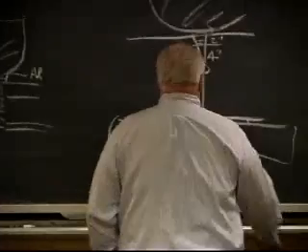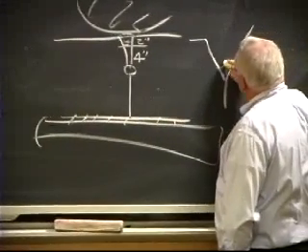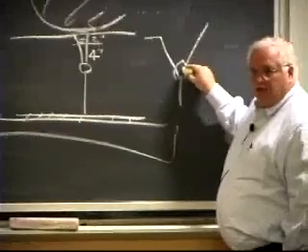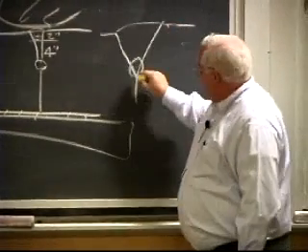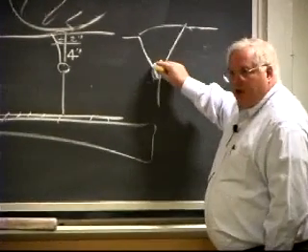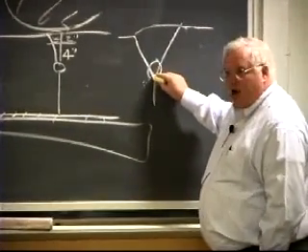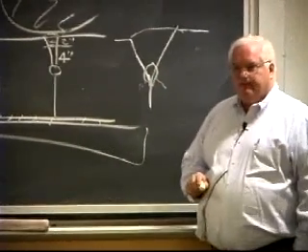Yeah, I got a question. I don't know much about materials, so tell me about when you drill that hole, what are you getting rid of? I'm getting rid of, well, at a root pass, when I'm doing an arc weld, they call it the root pass because it's at the root of the weld. This is the face of the weld up here. But when I put that first pass in, I've got lots of heat flow, and I don't have a great geometry, and I will typically end up with some lack of fusion defects when I do that.